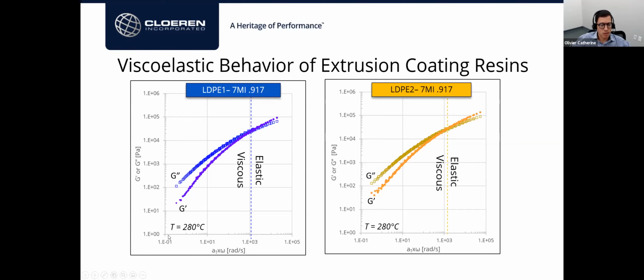And you can see as the frequency increases, the elastic component is getting closer and closer to the viscous component. And eventually we have a crossover and the material becomes elastic dominant. So this crossover point is a very interesting characteristic of the viscoelastic behavior.